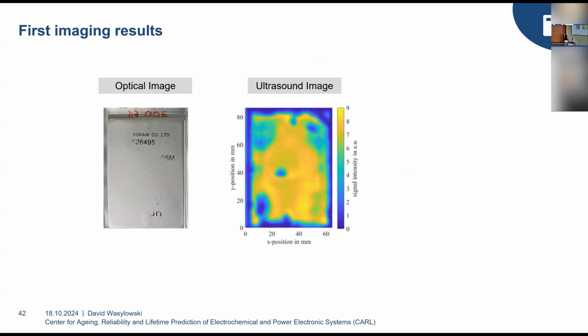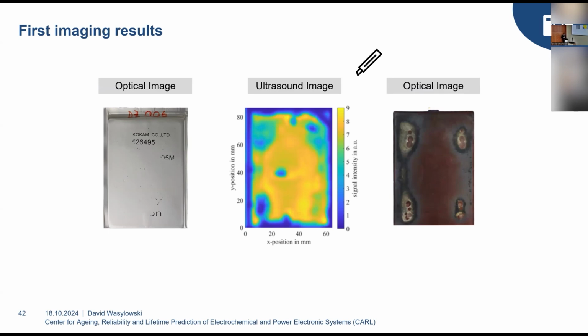And the only way to verify this is to actually disassemble the cell and take a picture of what's inside. And this is the optical image that we got from the anode. So we were very excited that these two images are so congruent. So this method seems to work. We seem to actually be able to visualize what's inside the battery. But there is one problem here. First, we hypothesize that there is a gas accumulation in this lower left-hand corner. But if we actually look at the optical image, there seems to be a deposit here.